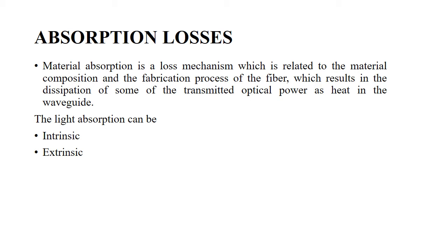Intrinsic absorption is caused by interaction with one or more of the major components of the glass. Extrinsic absorption is caused by impurities within the glass. That is, intrinsic absorption is by the basic constituent atoms of the fiber material, and extrinsic absorption is by impurity atoms in the glass material.